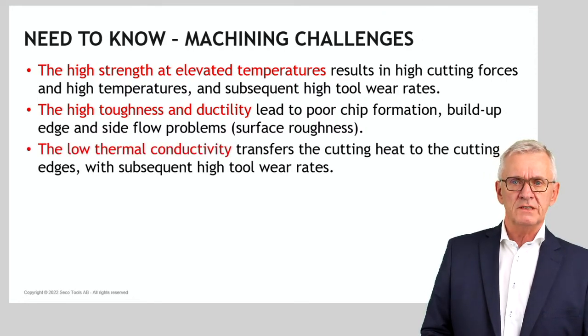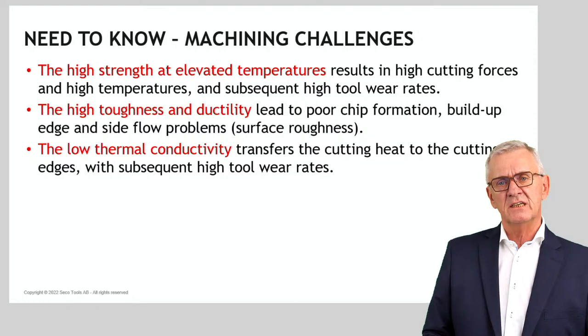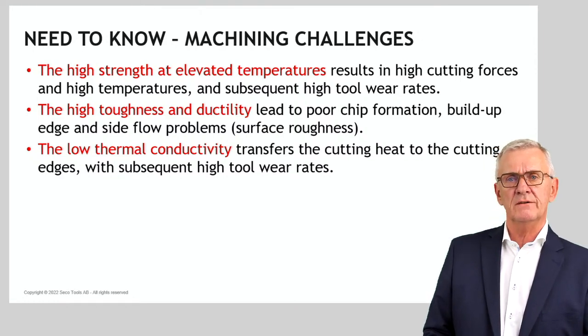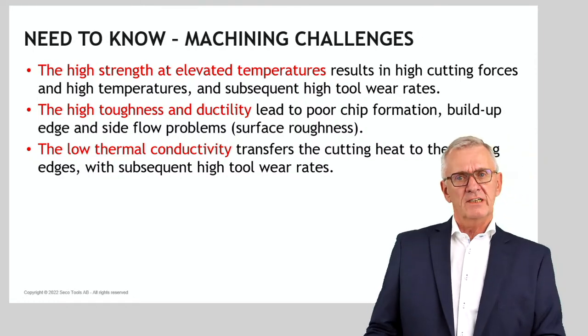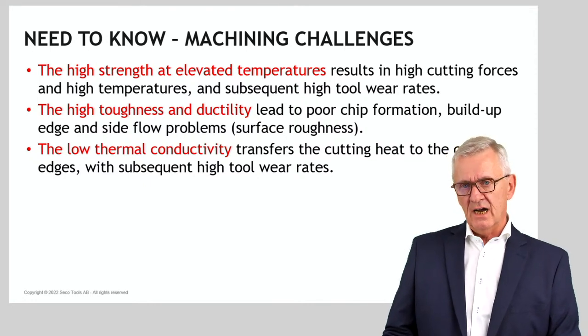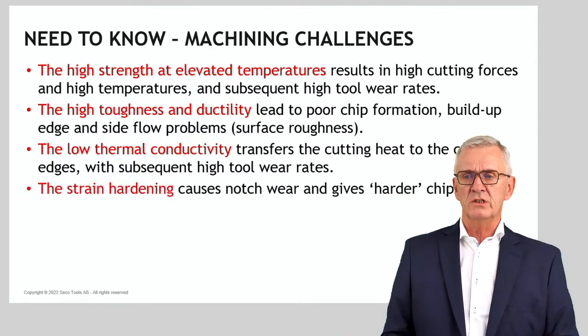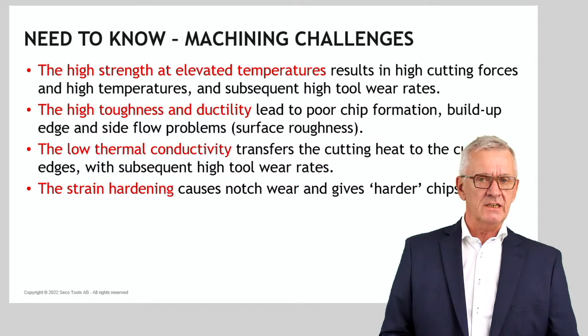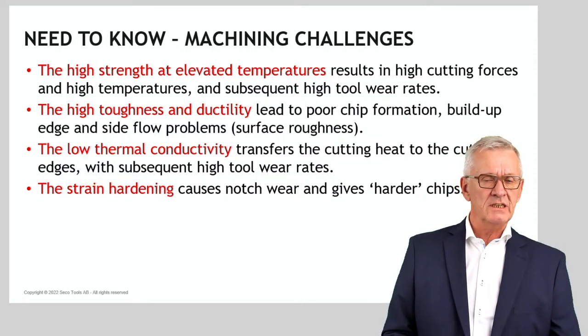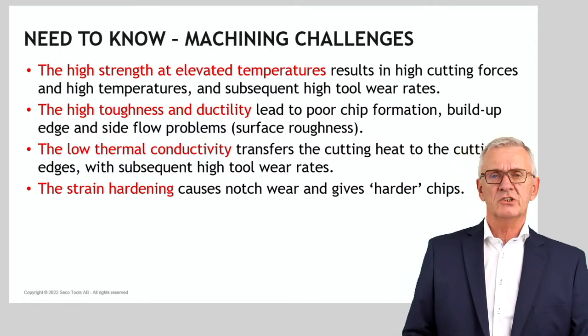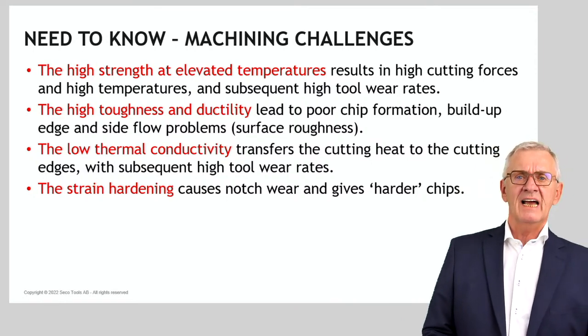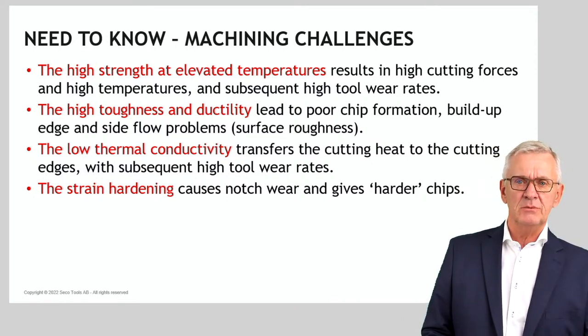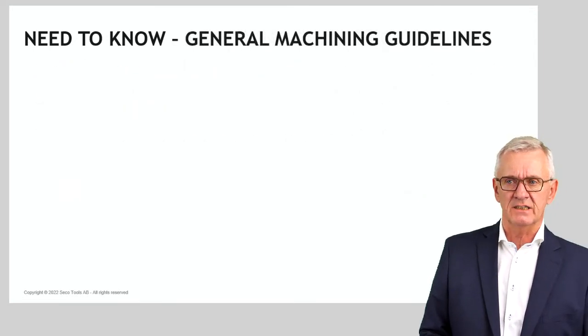Low thermal conductivity, we discussed briefly. That means the heat is not so easily transferred away from the cutting zone. The consequence is that the cutting temperatures are rather high in the cutting zone when we machine these materials. And strain hardening and precipitation hardening, the little footnote I mentioned, gives us extra notch wear and will give us harder chips than what we thought in the beginning. Because you remember I said a chip is also deformed, and a chip could also be suffering from strain hardening.